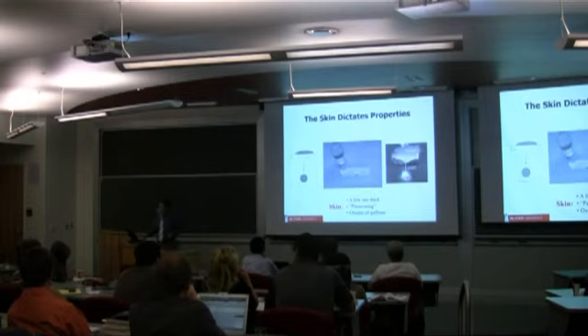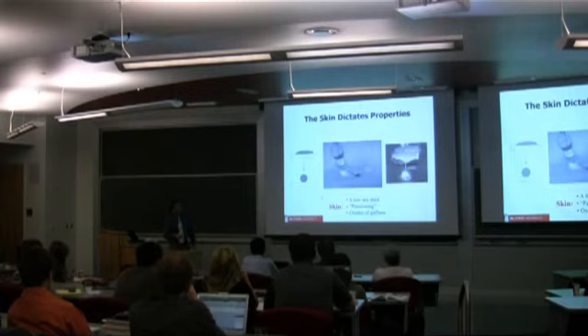And so to kind of convince you, this is a video where we've spread the liquid out onto a glass slide. And if you expose this to acid, you actually can remove the skin because it's so thin, it goes away very quickly. In fact, the vapors are enough to do it. And in the absence of the skin, it beads up just like you would expect mercury or any high surface tension fluid to do. Okay, so the key thing is we have an oxide skin of gallium.